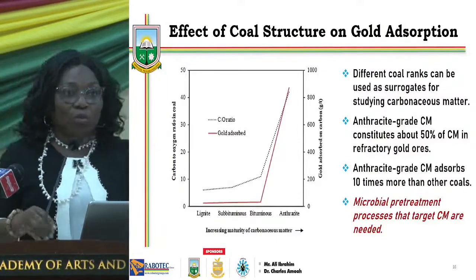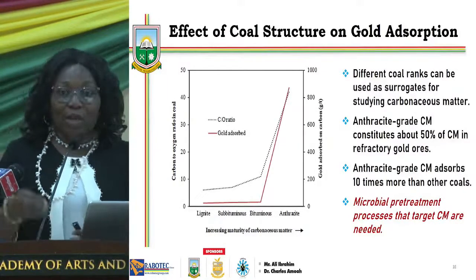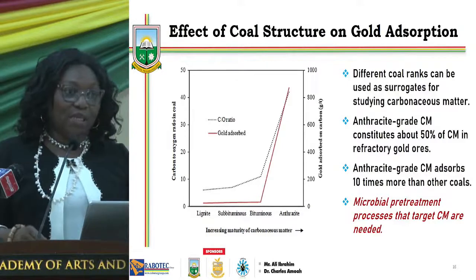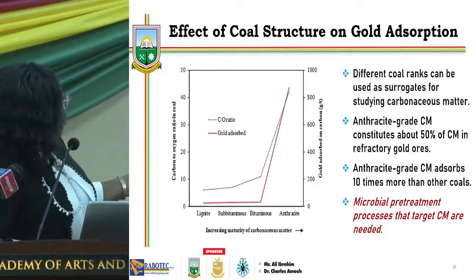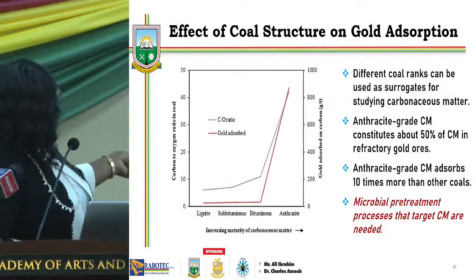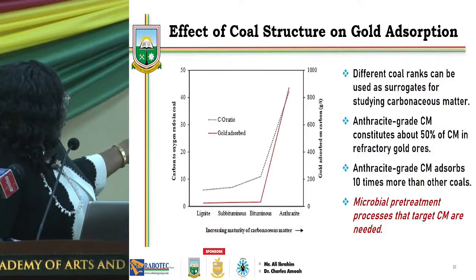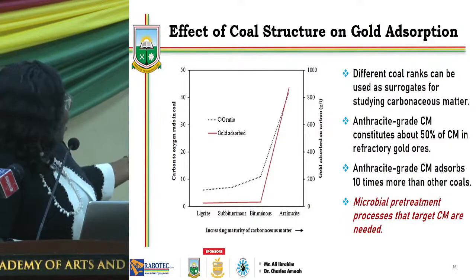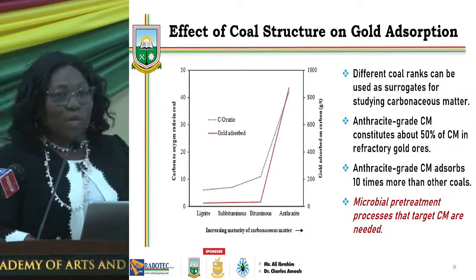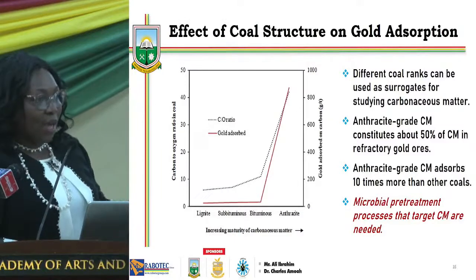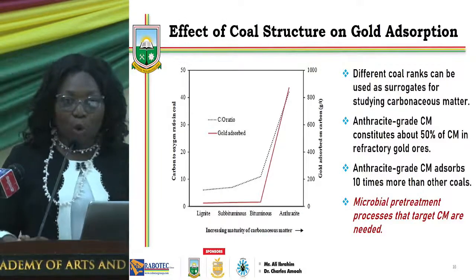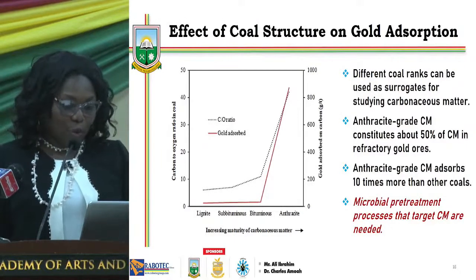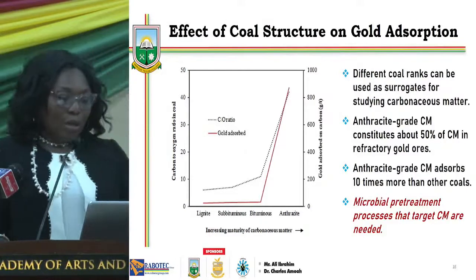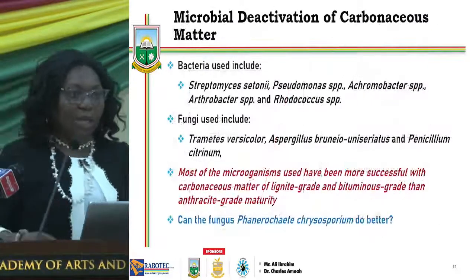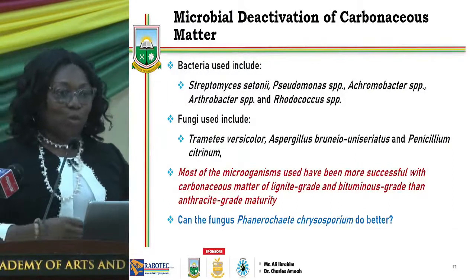So we tried finding the carbon to oxygen ratio, and it is very clear from this diagram that the left-hand side is carbon to oxygen ratio, and the right is gold adsorption. So the higher the carbon to oxygen ratio, the higher the gold adsorption. And that is highest when we have a more mature form of carbon. Now, looking at this, it means that anthracite can adsorb more.